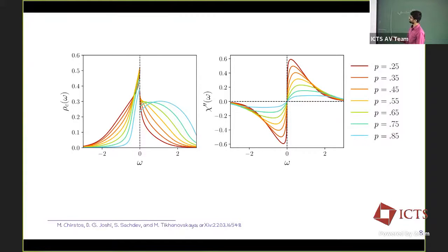But the main information that you want to take from here, for example, if you look at chi double prime, you can see that in this blue curve, which is in the very large doping limit, there is almost linear behavior, because the exponent in the Fourier transform chi double prime of omega is eta minus 1. So if eta is approaching 2, then you approach a linear curve, and this you see as you go towards higher doping. Whereas at lower doping, you see that there is a very strong power law, because eta is very much away from the value 2. And in the extreme case, when you would have some SYK-like exponent where eta is 1, then in the low frequency limit, it should approach a constant value.